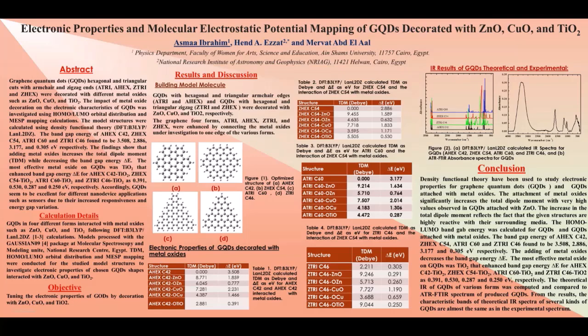The total dipole moment, HOMO-LUMO orbital distribution, and molecular electrostatic potential mapping were conducted for the studied model structures to investigate electronic properties of chosen graphene quantum dots shapes interacted with zinc oxide, copper oxide, and titanium dioxide. Objective: tuning the electronic properties of graphene quantum dots by decoration with zinc oxide, copper oxide, and titanium dioxide.